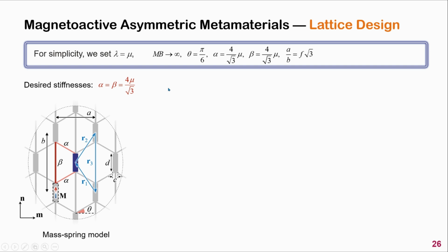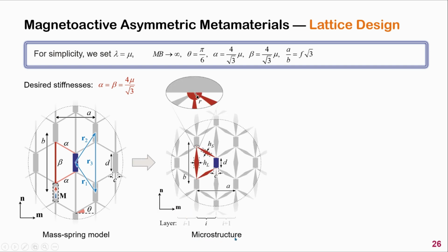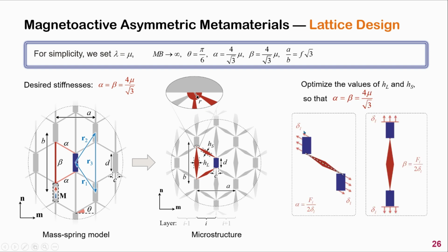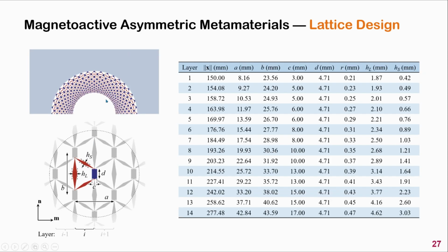Okay, till now, the above analysis is based on the mass spring model. Now, let's consider the realistic microstructure model that corresponds to the ideal mass spring model. In the microstructure model, the rhomboid beams act as springs, and the hinge contacts are joined using a semicircle with a very small radius. Then, the last step in designing the lattice cloak is to optimize the geometric parameters of the rhomboid beam for the required stiffness parameters alpha and beta. For given cloak inner and outer radius and the number of layers, the geometric parameters for the microstructure located in each layer can be determined as shown in this table.